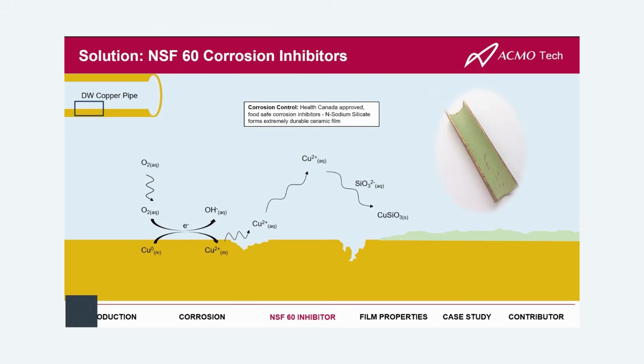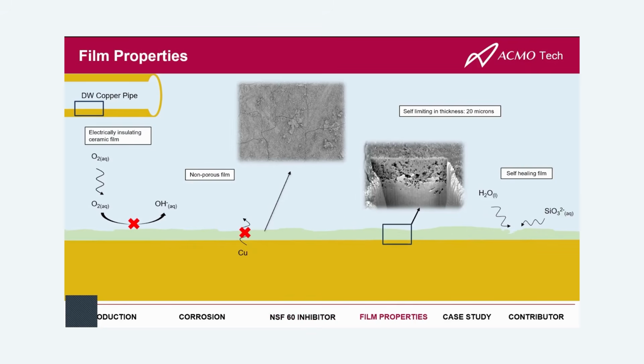And this technology has been around for hundreds of years. And what it does is it forms this ceramic coating, and it reduces the heavy metal content that you are consuming in your water. Now, how does it protect the pipes underneath? Well, there's a few ways. So first of all, on the left, the film is electrically insulating. So any dissolved oxidants that want to rip off electrons from the film will not be able to do that, because it will act as a barrier electronically for corrosion, while still not reducing thermal efficiency.